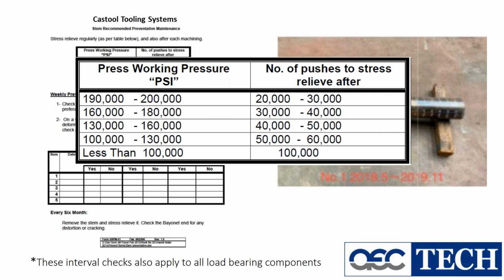That's two different things. If we have a 40-inch long container pushing on an 8-inch die, the pressure is approximately 94 to 96,000 PSI on the face of the dummy block. If we then take that same 8-inch container and make it 52 inches long, that 12 inches longer container takes the face pressure on the dummy block up to 104 to 106,000 PSI, but still remaining at that 94 to 96,000 on the face of the die.